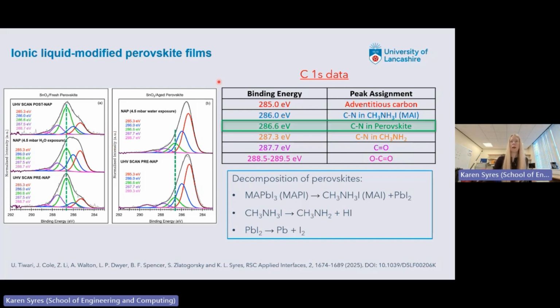So what we're looking for here is this particular peak. The green peak here is what we want. This is that CN bond in the perovskite, and that means that the perovskite is in the condition that we want it to be in. In the fresh sample, you can see we've got lots of that, whereas in the aged sample, there's not very much of it, and that is because the perovskite has decomposed.